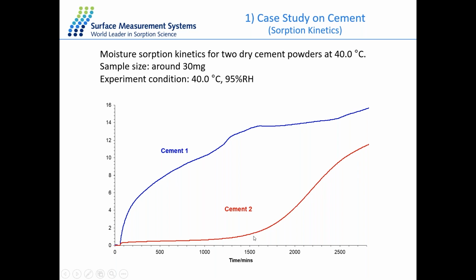Well, the cement 2 sample shows a different trend. It's very stable, has very little increase initially, and then is followed by a larger increase in the mass after about 24 hours of exposure to humidity. So from the result, we can conclude that the cement 2 sample might have a longer storage time compared to the cement 1 sample during processing and performance. So these two simple studies on the cement sample just illustrate how DVS can be used to study cement-based materials over a wide range of temperatures and humidities.